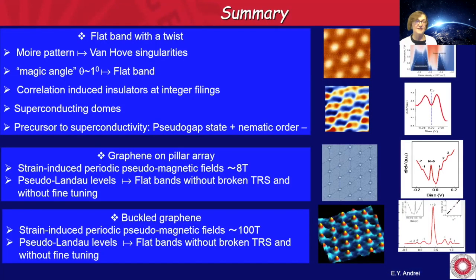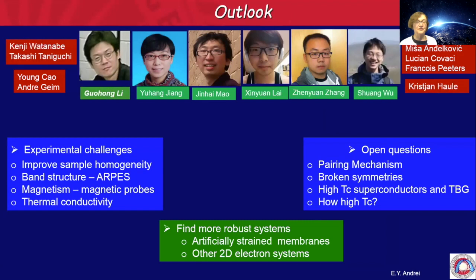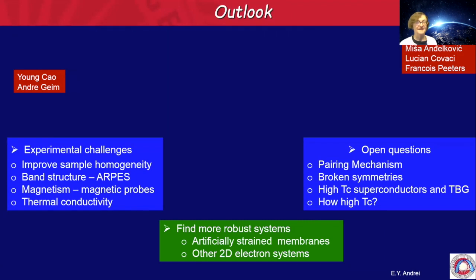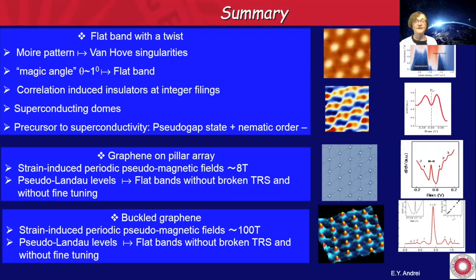And this brings me to the summary. So I covered three ways of creating flat bands in this case, all of them involving graphene. So first we started out with overlaying 2 layers of graphene or any kind of crystals, which will give you a Moiré pattern, which gives rise to Van Hove singularities when you have hybridization between the 2 layers. At a magic angle of about 1 degree, you get a flat band. And that gives rise to various very interesting correlated phases when you bring the Fermi energy into these bands, especially when you have integer fillings of the Moiré cell: superconducting domes, and we see a precursor to superconductivity, which is a pseudogap and the nematic order.